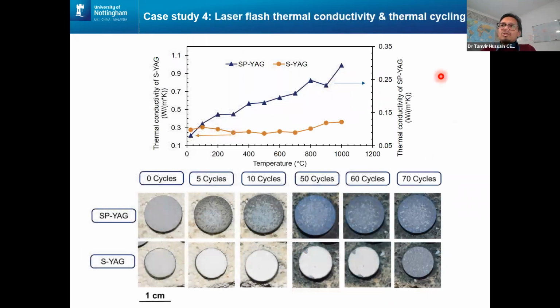What we're interested in is also thermal conductivity. So we have a laser flash thermal conductivity measurement kit. Typically, when we are working with the state-of-the-art TBCs, we are operating around 1 watt per meter Kelvin. And what we found out is, if we work with YAG and a solution precursor, we can drop the thermal conductivity quite significantly, different scales, and that one is for thermal conductivity of SP-YAG.